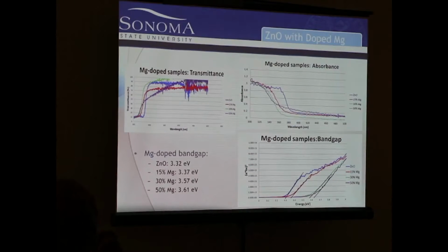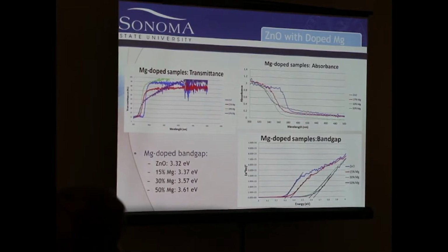So with magnesium, we expected it to shift and move to higher electron volts, and that's what we were able to see. So the red one represents the 15%, and we got about 3.37 electron volts. And then 30% magnesium, we got 3.57, and then 50% we got 3.61 electron volts. And then after about 50%, the highest I could really get it to is about 3.7 electron volts, but also the quality went down, so I focused mainly on 15 and 30.